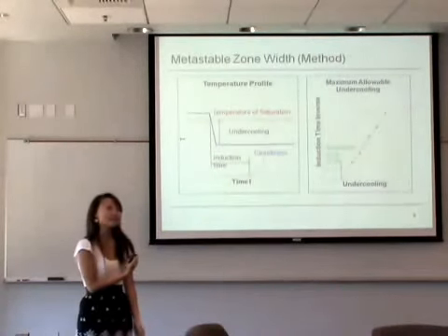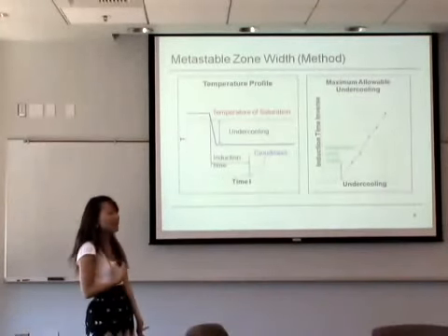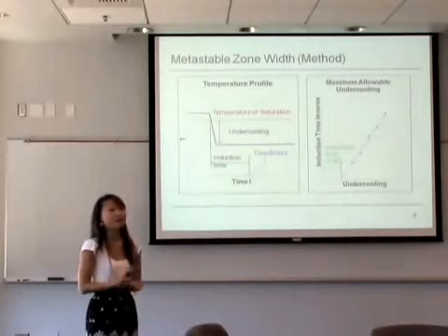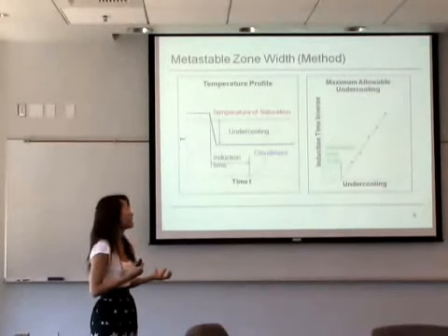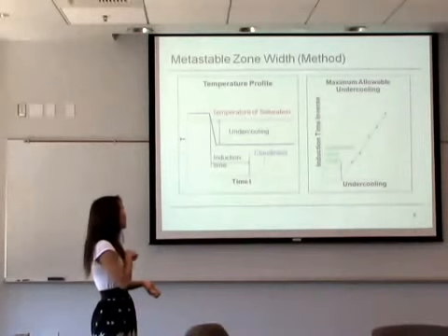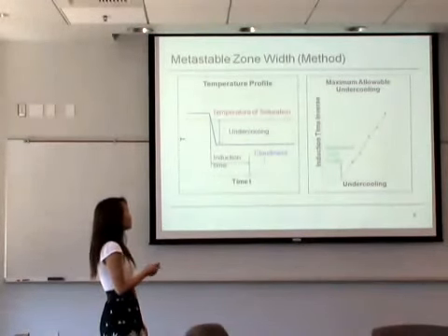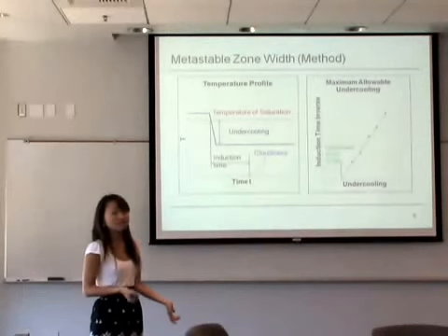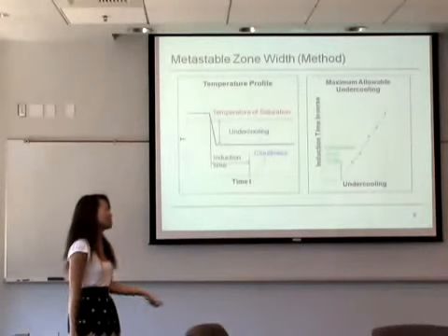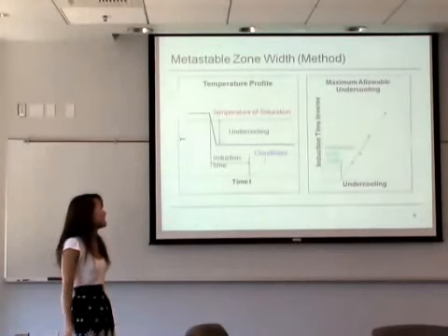Afterwards I looked at the metastable zone width, which is basically taking the crystal solution at a temperature above the saturation temperature and then plummeting it so it can start forming crystals, and looking at the induction time. For whatever induction time, an inverse induction time equal to 0 means the induction time is infinity. That means no crystals would spontaneously nucleate.